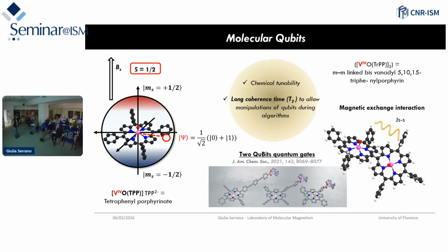What chemists can do, and this is very interesting for the new trend, is also to connect and bind in a controlled way two or multiple spin systems. So we can have a ligand, like here you can see a single vanadyl tetraphenylporphyrin with a vanadyl ion, which is the spin 1/2 state. Here you see a dimer, a vanadyl porphyrin dimer, in which we can, through the backbone of the ligand, control the magnetic exchange interaction between the two ions. Then, of course, this would be very important when you want to process more complex quantum algorithms and you want to create some quantum logic gate.